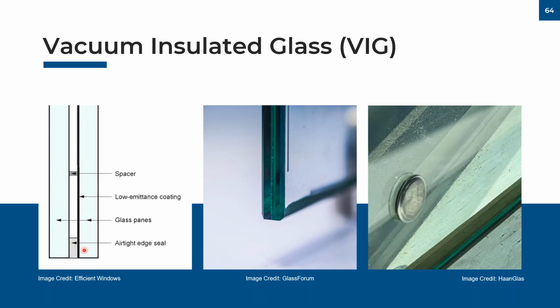Now, these spacers are a big subject to analyze very closely. These spacers can be made of several different materials, ranging from polymers to a glass frit to metallic edge seals, right here. Each of those has its own different life expectancy, with the metallic edge seals really performing the best. And it's really a factor of how thick, dimensionally, that metallic spacer is. The thinner the dimension, the less likely it is to perform long term.